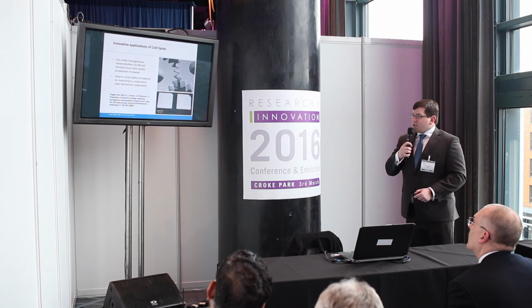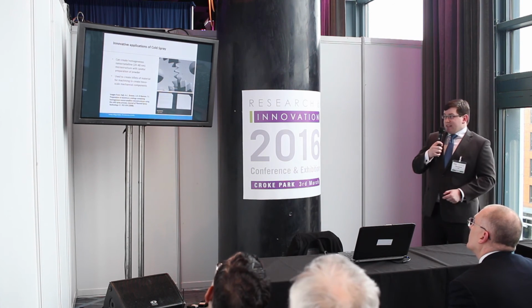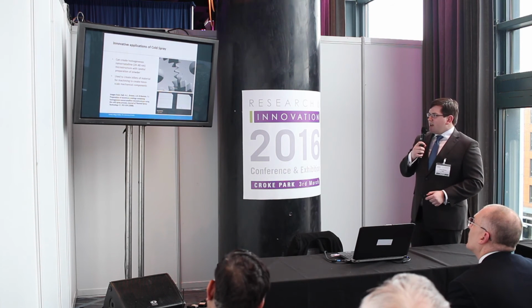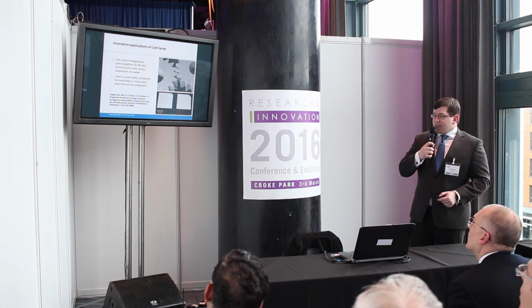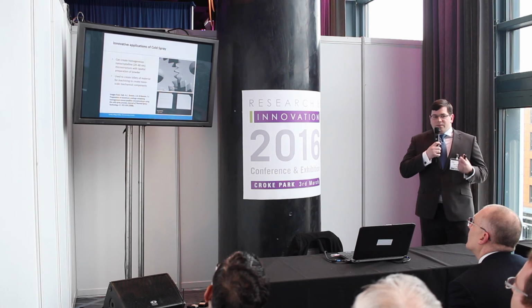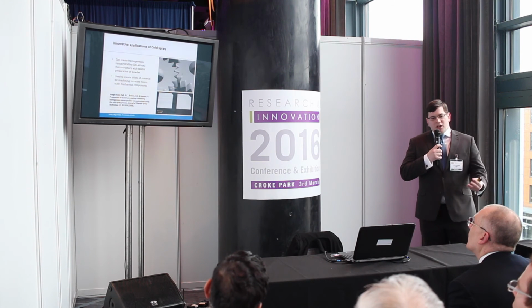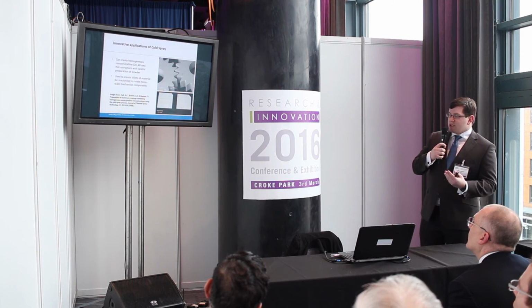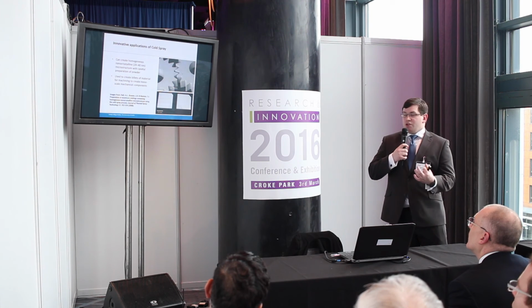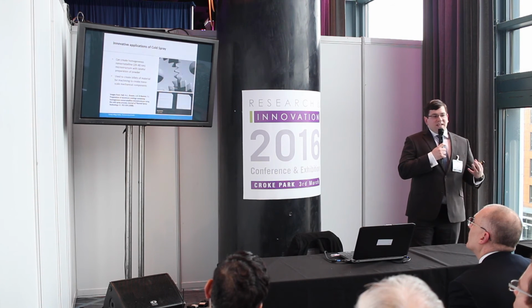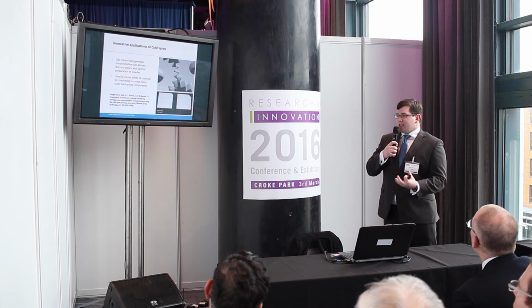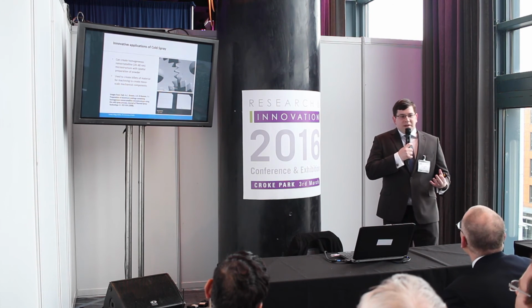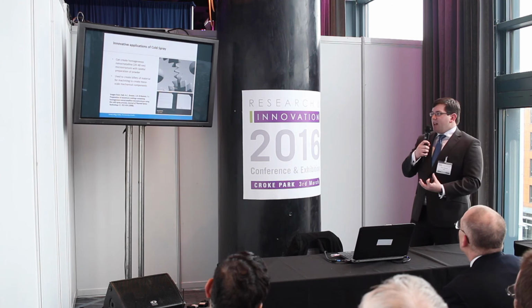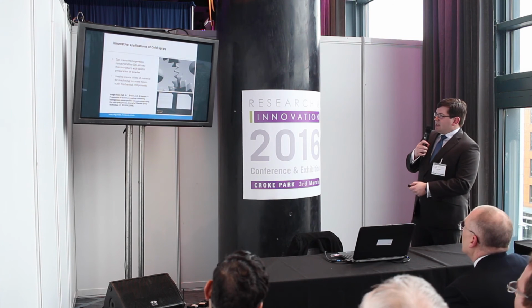On the nanocrystalline microstructure side of things, this actually really impressed me when I saw it. This is from a paper by Hall et al., where they took nanocrystalline powder, ball milled it to make the grain structure even finer, sprayed it to create a billet of material, and then machined that billet to create mesoscale mechanical components such as these gear teeth here.